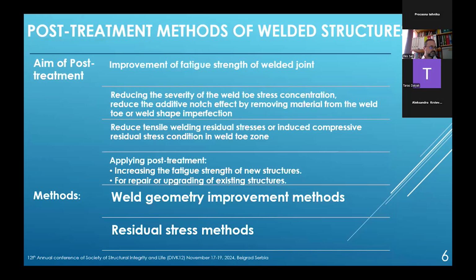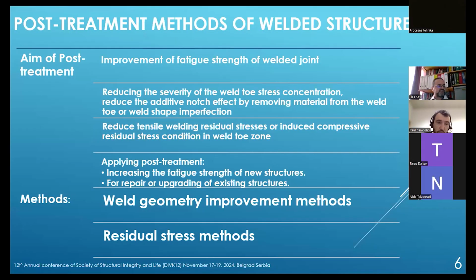fatigue properties. If we move forward to the post-treatment methods, first of all, I want to explain the aim of the post-treatments that we investigate in my research topic. The main issue is to improve the fatigue strength of the welding joints. That is basically applied with two approaches. The one approach is that we want to reduce the severity of the weld toe stress concentration by reforming the weld toe to eliminate the imperfections and give a much smoother transition between the weld surface and the material surface.